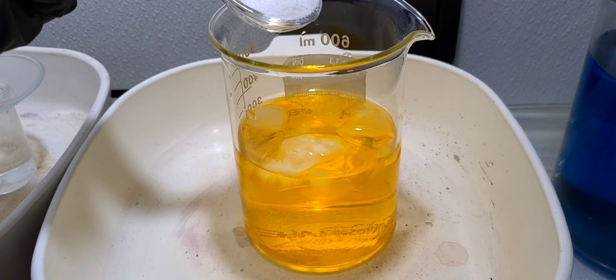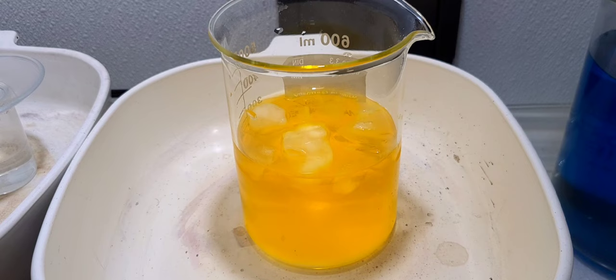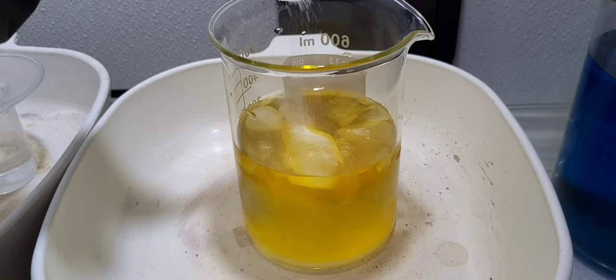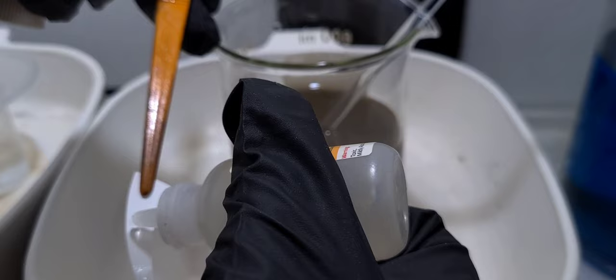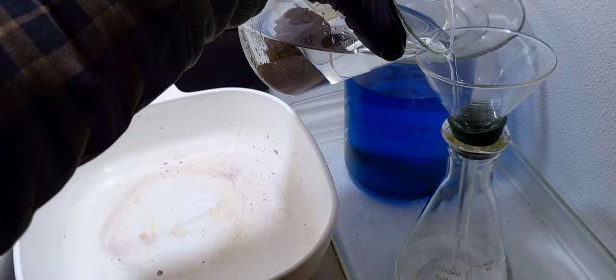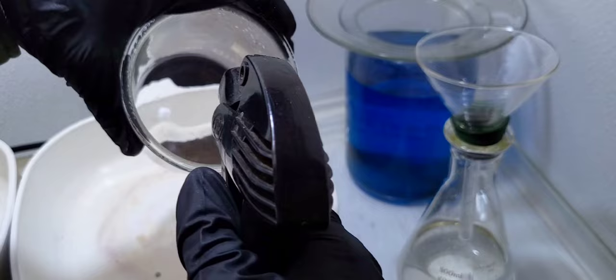Here I'm about to add our sodium metabisulfite. I kind of have it pre-measured so I know how much needs to go in there, so I'm just going to dump it in. As it dissolves it starts to react with the gold in solution and drop that gold out. That black is actually gold powder that you're seeing coming out of solution. We test it again with our stannous chloride — clear, nice and clean. We have all our gold out of solution. I let it settle and now we're going to decant that off and start our first rinse procedure.